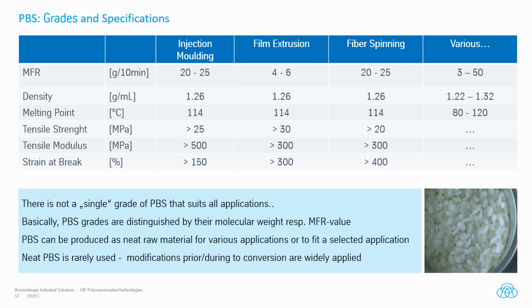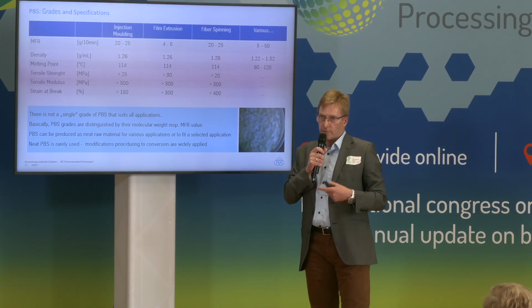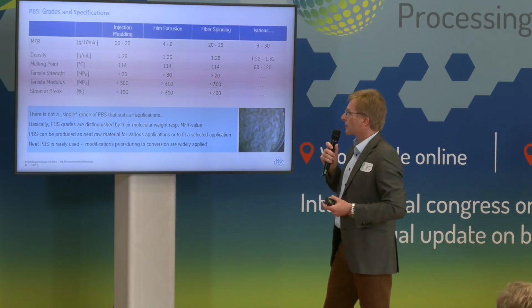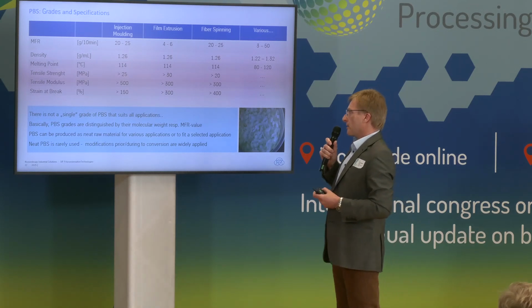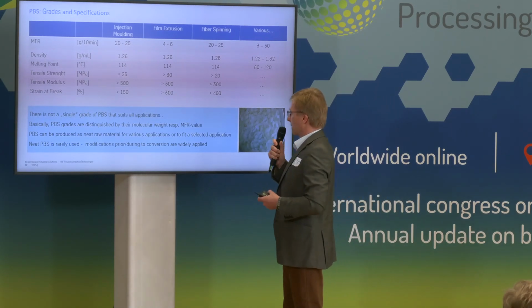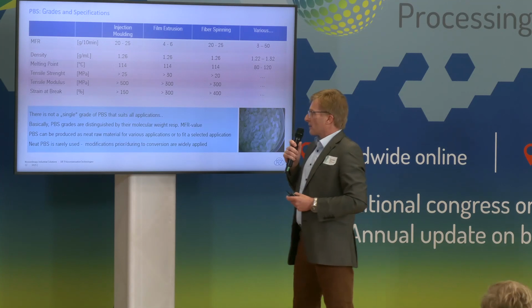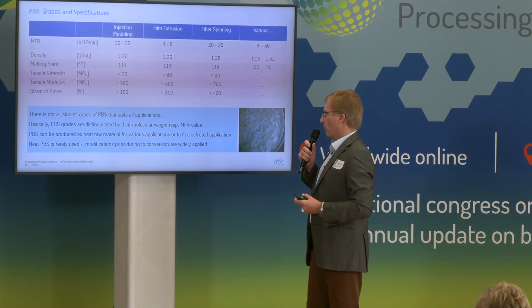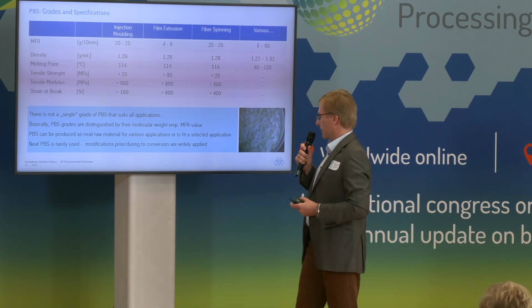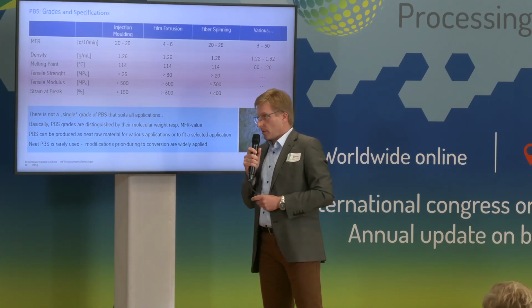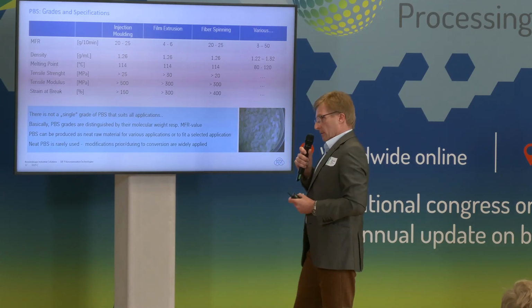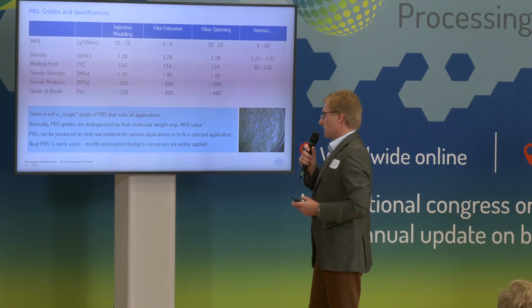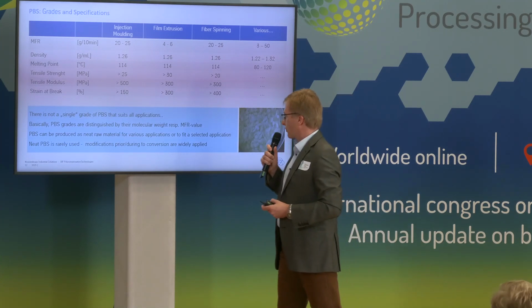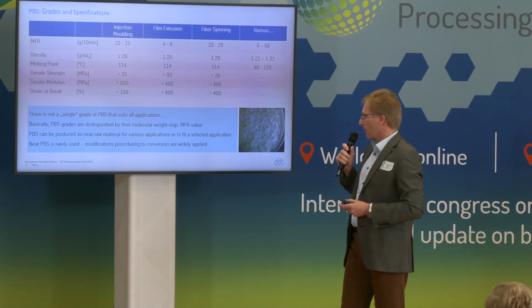That's why I said you have to consider already at the manufacturing of the PBS what it shall be later on, and what additional requirements you have regarding additives and melt modifiers. Basically, PBS grades are distinguished by their molecular weight, respectively MFR value. PBS can be produced as neat material for various applications or to fit one selected application. But for this neat PBS, typically a modification is made during or prior to conversion before it's really applied.